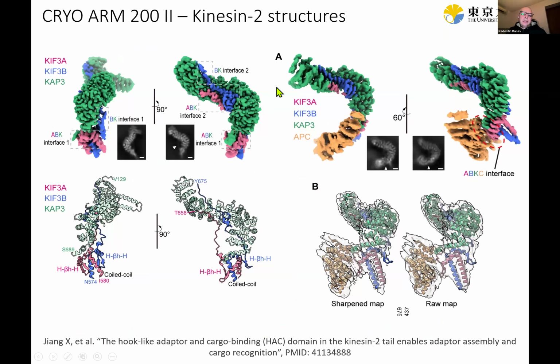Now, another practical, real-world application was in collaboration with Jiang from Kikkawa's lab. He's working on structural studies of kinesin, in this case kinesin 2, a heterotrimeric complex of the kinesin together with the adapter, and then also with the adapter and the cargo. So we have two structures. One is without the cargo and the other one is with the cargo. This is the first time such a thing has been structurally observed. The structure without the cargo was behaving much better, so we had more orientations and the structure was nicely isotropic, let's say. The one with the cargo suffered from very strong preferred orientation, as you can see here. So we have streaking, but Jiang was still able to build a decent model out of this.